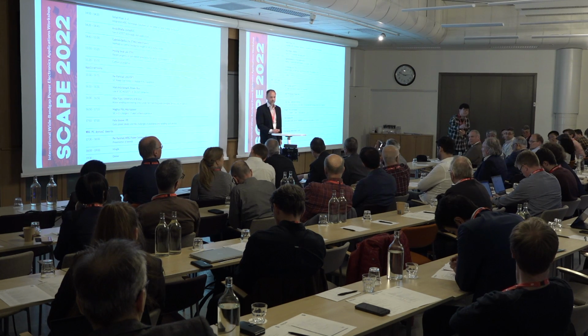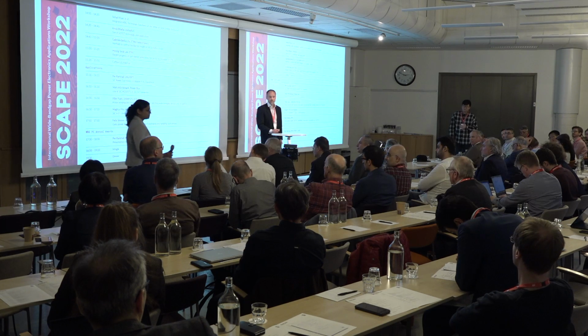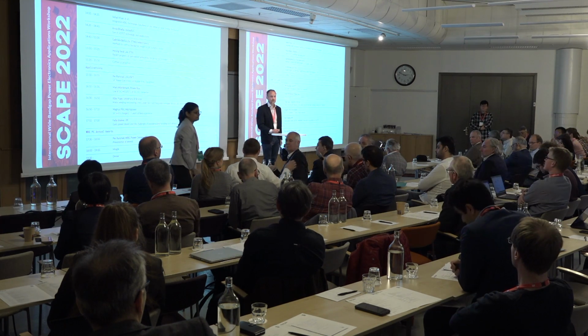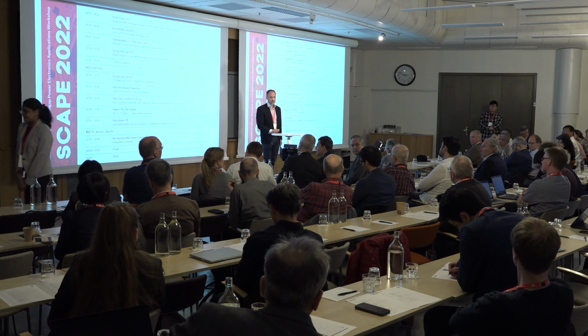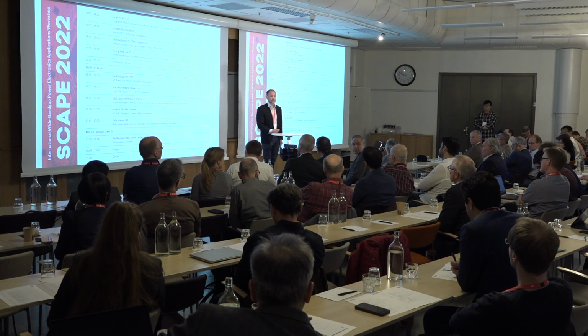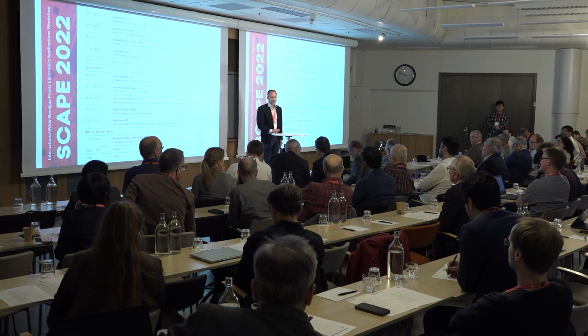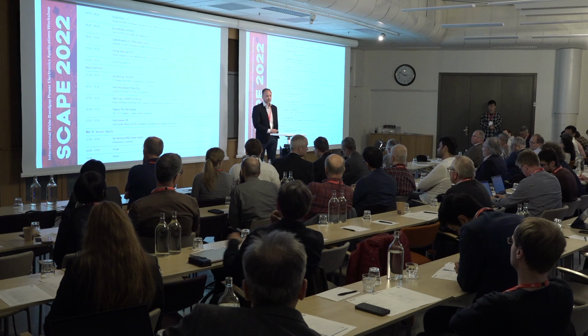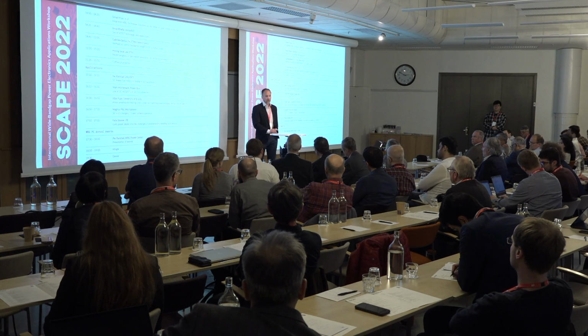Here's the question. The question is regarding the short circuit capability between generation 2 and generation 3, M2 and M3. Have you had any improvement? No, the M3S is developed for high efficiency, so short circuit capability is not as large as in the M1, which has a higher RSP. This is something we're working on, and the M3P that we're releasing has better short circuit capability, so that at the expense of RSP, we have one product offering here with better short circuit capability. But that's on the order of 2 microseconds.